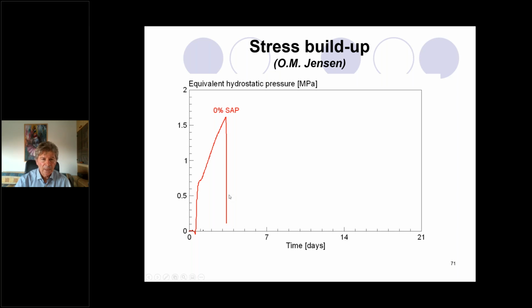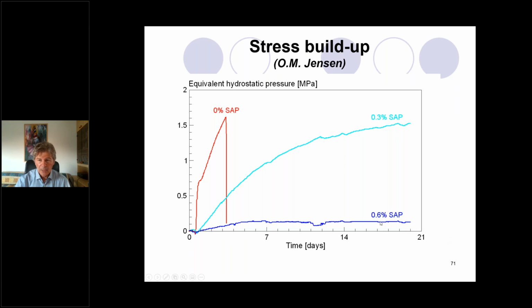And when we introduce some internal curing agent, we have a slower build-up of the stresses. This is with 0.3% of superabsorbent polymer introduced. Moreover, the lifetime of concrete is extended dramatically. We don't have any cracks within 2 or 3 weeks of monitoring. And if we introduce a little bit more, 0.6% of superabsorbent polymer, we have almost complete compensation of the stresses. Very nice result. No risk of cracking, nothing.